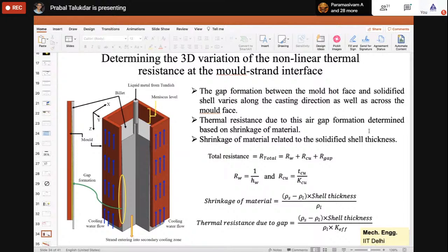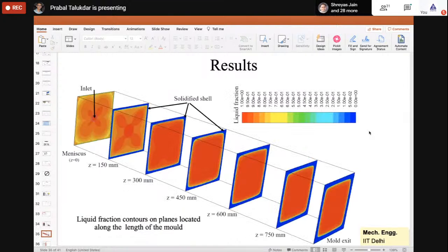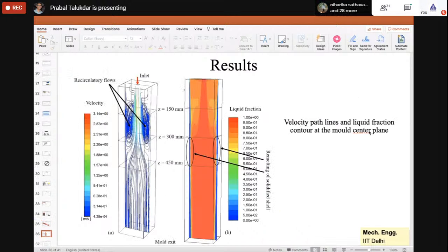The same problem. Now we are not doing it like a two-dimensional problem, marching in the flow velocity direction, from top to bottom. It's not like that. Now it's a steady state problem with a three-dimensional mold, and we have done it in Fluent, and we have got similar results. But many things you can see from CFD results, like this remelting phenomenon which we observed previously. This 2D model is not able to capture that, because in the 2D model there are no turbulent flow simulations, right? Only in the 3D model do we have fluid flow simulation, so this gives you more insight, but of course at the expense of a large amount of time.